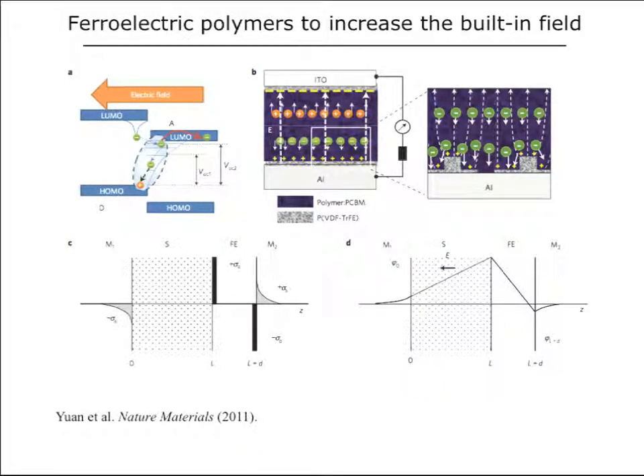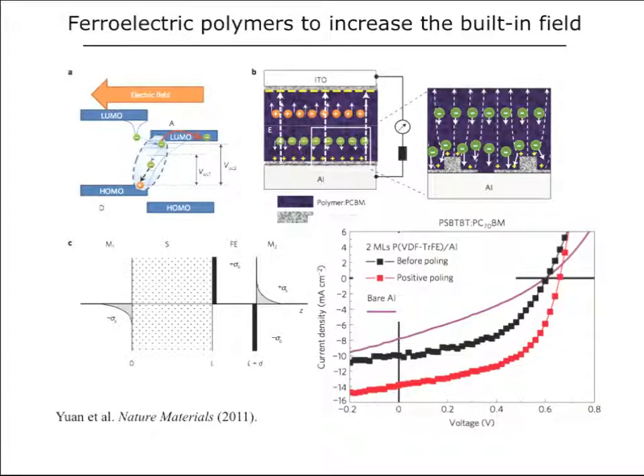So one can plot the charge density in the device, and at the dielectric layer, the ferroelectric layer rather, we get a large separation of charge. And what that does is to increase the built-in field in the active layer. So what Yuan's group did was to show that the fill factor of this device increases, the short circuit current increases, the VOC increases a little bit. So a nice bit of device engineering. And I like this because it uses a new material and shows us something about the photophysics as well.